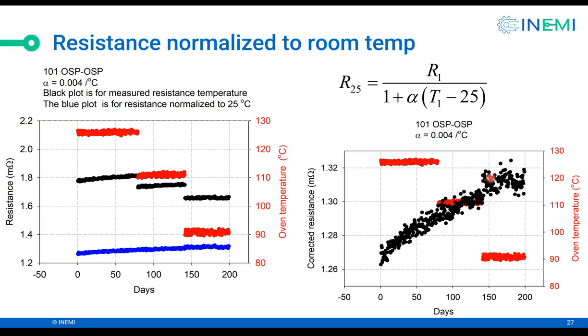So what we do is we measure the resistance of the solder joint as a function of time. We start off with the oven temperature at 125 degrees, and we measure the resistance, which is the black line. Then we drop the temperature to 110 degrees. That's the oven temperature, and the resistance drops, but it increases slightly. There's a jog, a slight increase.